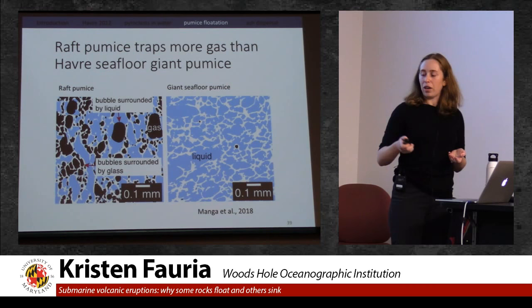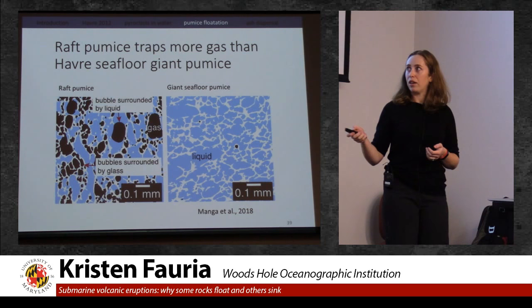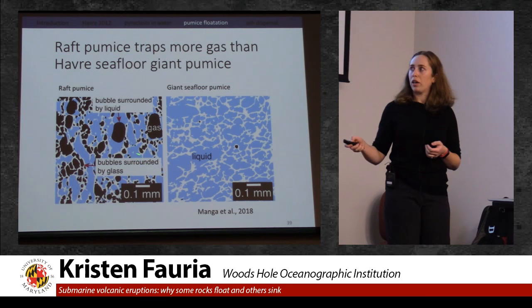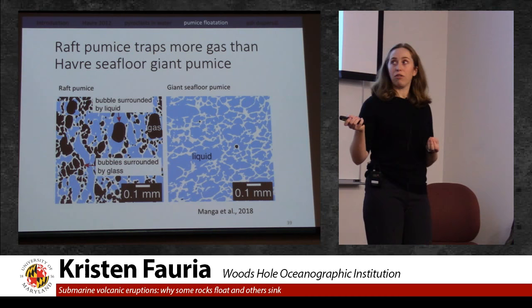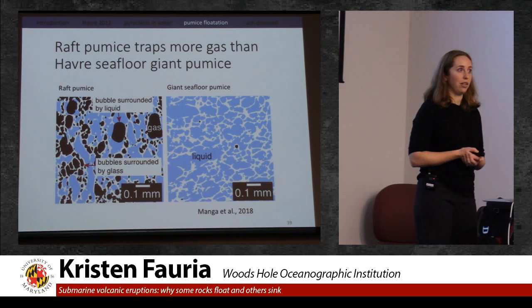And so now I'm comparing these 2D slices between the raft pumice and the giant pumice on the seafloor. And we find that, where the white is rock, the blue is water, and the black is gas, the raft pumice stay nice and gassy and full of air, whereas the seafloor pumice, the giant pumice, are able to ingest more liquid water, not trap gas, and therefore not remain buoyant because they don't have enough gas inside of them.